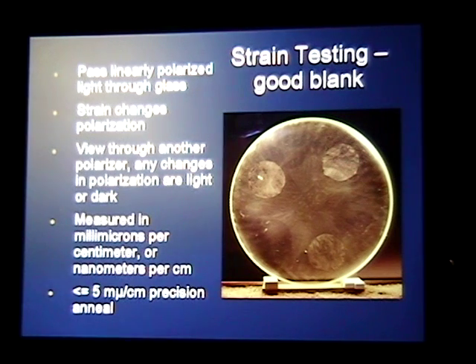So this is before the glass. Light goes through the polarizer, through the glass, and if there's any strain within the glass, that will change and rotate the polarization of that light. And then you put another polarizer in front of it and turn that 90 degrees to the first one. So what you end up seeing as the polarized light comes through the glass and through the two polarizers is something, hopefully, that looks like this.